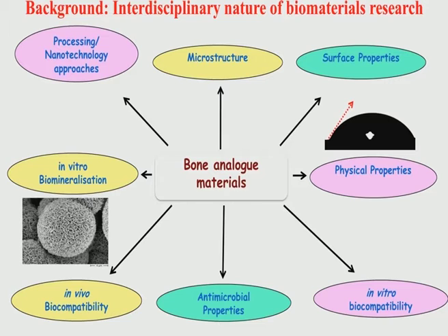Now, since bone has hydroxyapatite as one of its inorganic phases, if some material does not have hydroxyapatite as one of its microstructural constituents, it is very important to see whether this material can induce calcium phosphate nodule formation when immersed in simulated body fluid over a certain time period, which can be a few days to a few weeks.